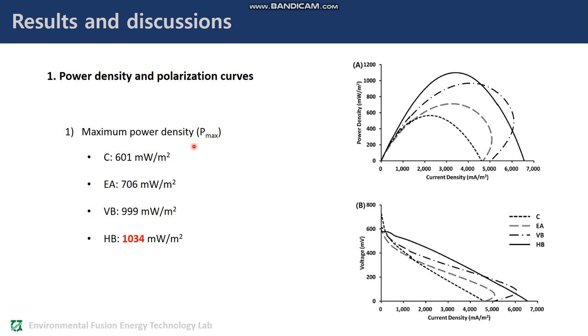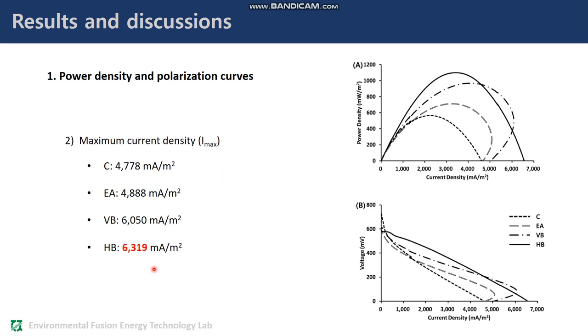Maximum power density in average was highest in the horizontally located carbon fiber brush anode, HB, with 1034 milliwatt per square meter, followed by VB, EA and C. Maximum current density in average was also highest in HB with 6319 milliampere per square meter, followed by VB, EA and C. However, optimal current density in average was highest in VB of 4137 milliampere per square meter, followed by HB, EA and C.